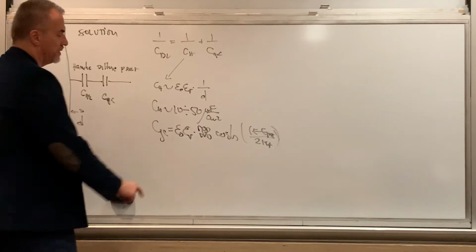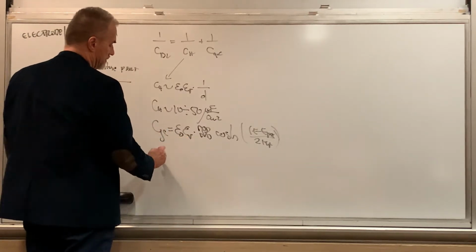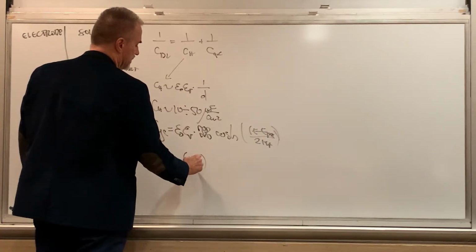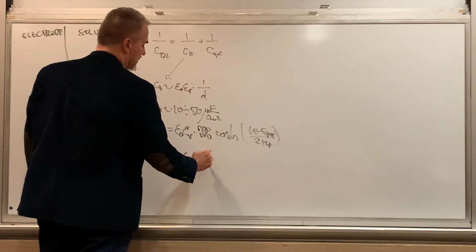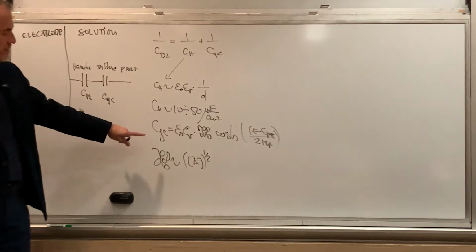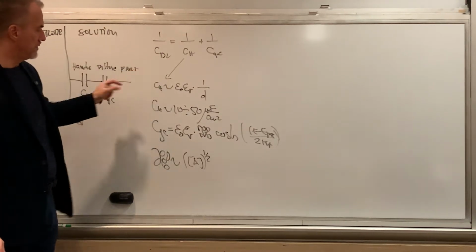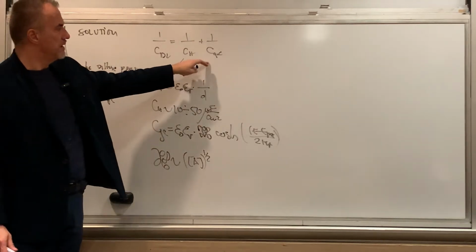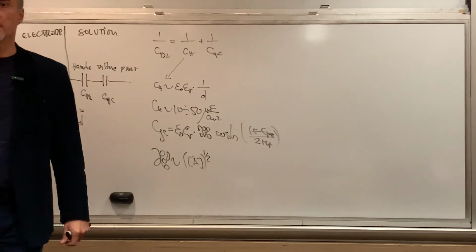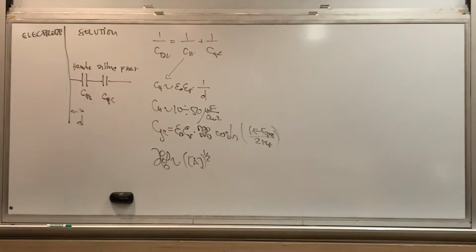And then, because of this inverse length being proportional to the square root of the concentration of our electrolyte, we talked about that at high concentration this is large and bigger than this, but in this configuration where we have series capacitors, then this term drops to 0, and eventually the Helmholtz layer is the one that is mainly contributing to what we measure as a double layer.